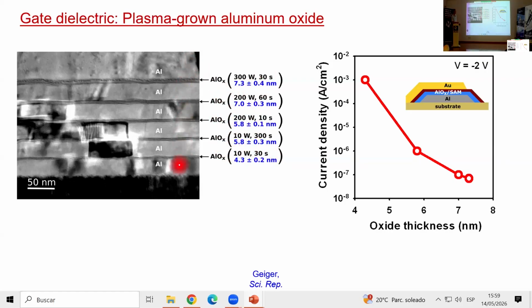So this is a stack where we've grown 5 different thicknesses of aluminum oxide simply by varying these 2 different parameters in different permutations here. And then this is what we get. We get thicknesses ranging from 4 nanometers to 7 nanometers. Okay, so we do have pretty direct control of that oxide thickness by setting these plasma oxidation parameters. Does that make sense? Yeah, yeah.